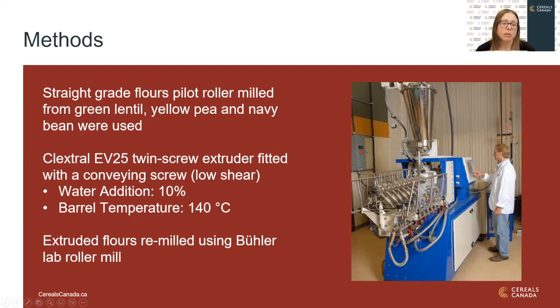So we used the twin screw extruder. The barrel temperature was 140 degrees, and we added 10% water to the flour. We used a conveying screw for this activity. This is a different screw configuration than what we would typically use to create a puffed product. And the reason why we did this was because we just wanted to heat treat the flour. And so the product coming out of the barrel, we wanted to stay as a flour consistency and not get a puffed product at the end.